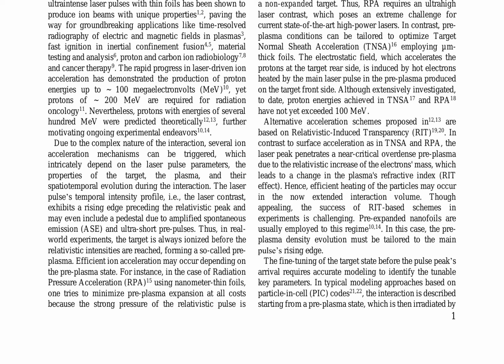They discuss various ion acceleration mechanisms, including radiation pressure acceleration, RPA, and target normal sheath acceleration, TNSA, which depend on the preplasma state. The research emphasizes the need for accurate modeling to identify tunable key parameters, particularly in the context of relativistic induced transparency, RIT, schemes. The authors suggest that fine-tuning the target state before the pulse peak's arrival requires a deep understanding of the interplay between ionization, collisions, and expansion. The study's findings have implications for applications such as laser-driven ion acceleration, material testing, and cancer therapy.